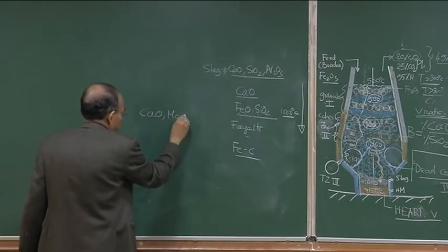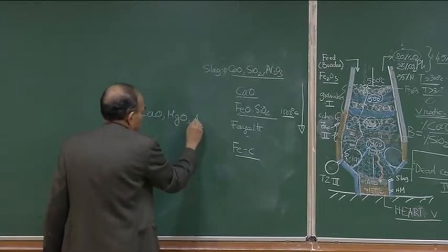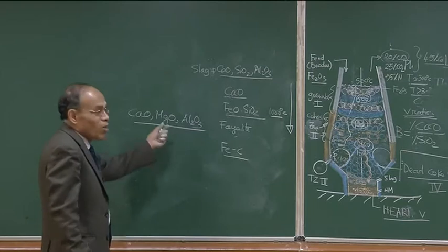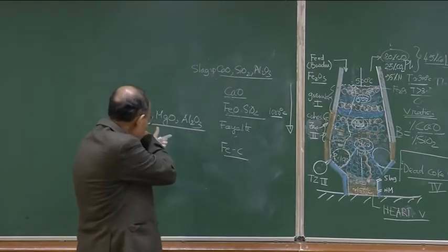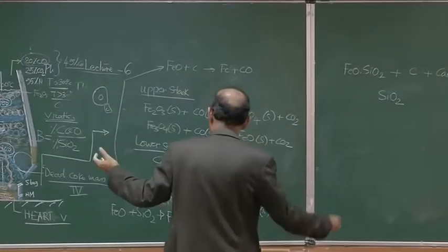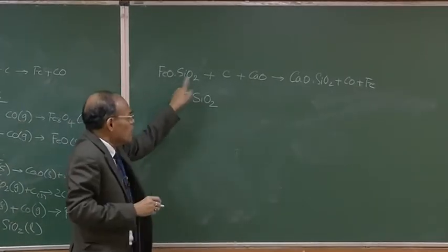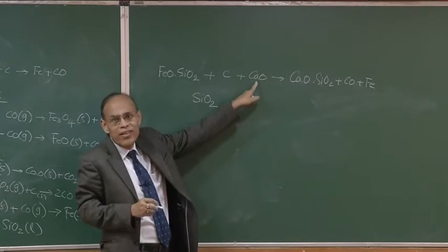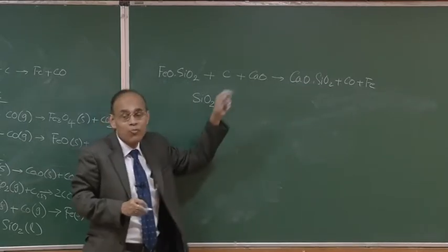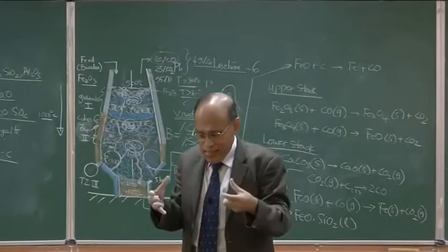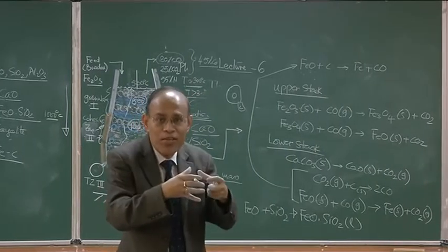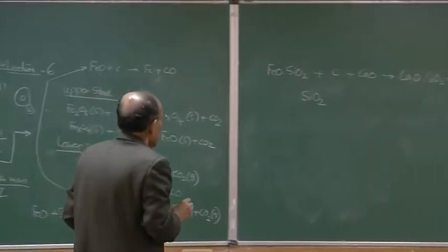They do not undergo reduction reactions. So basically these remain as they are, as I have indicated, and then they form the slag. They only replace certain oxides. For example, this is also possible. I could have written MgO here; that is also a possible reaction, and that will happen if MgO comes in contact. We must understand that these are all heterogeneous reactions; the reactants must come and meet at a location, and only then can the reaction take place.